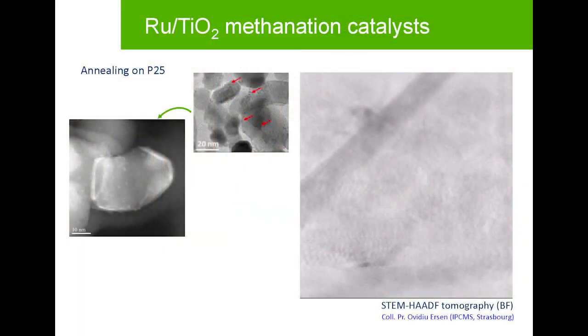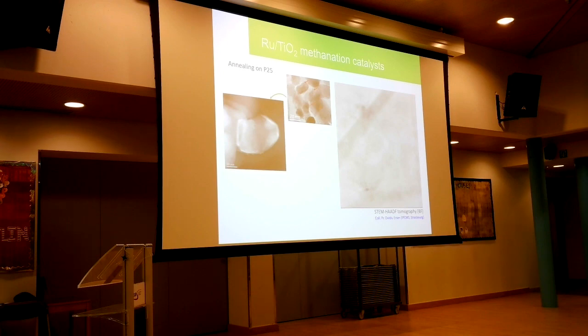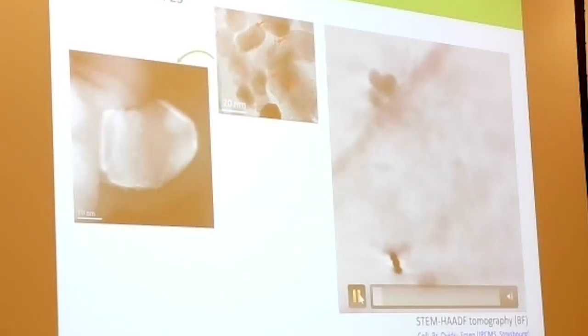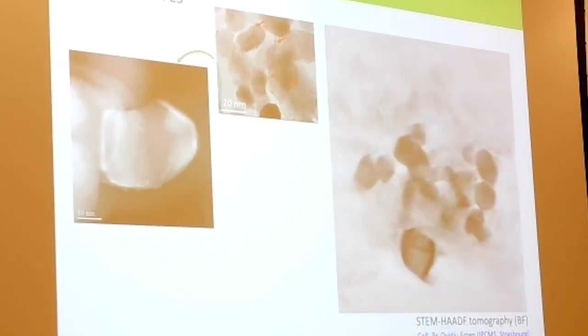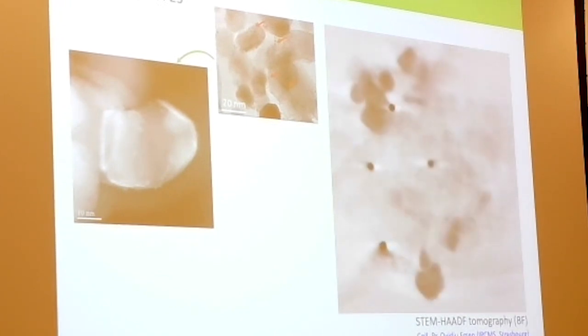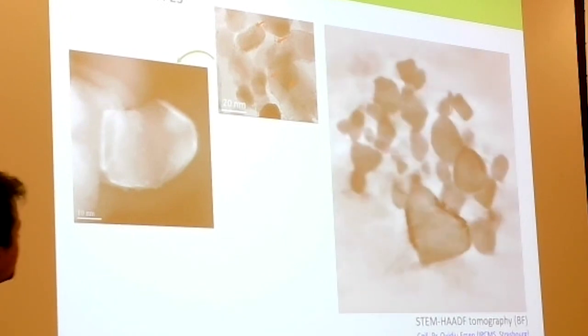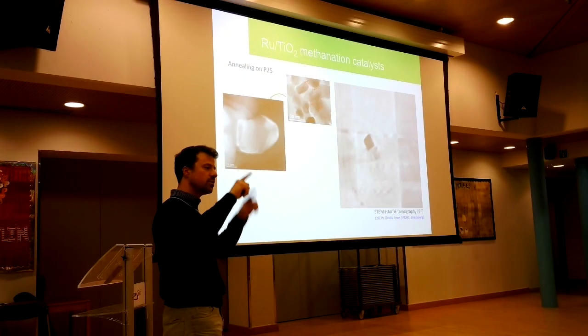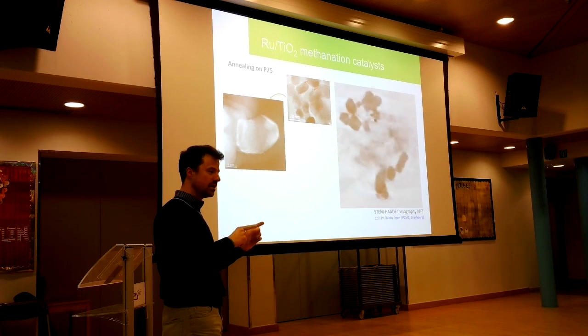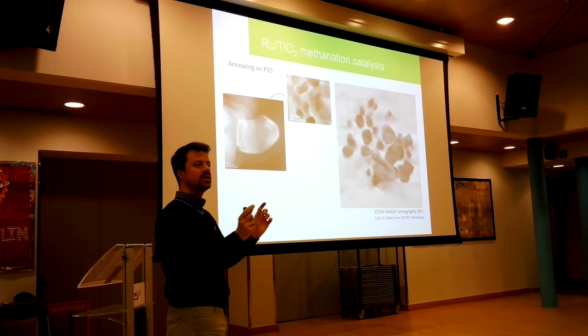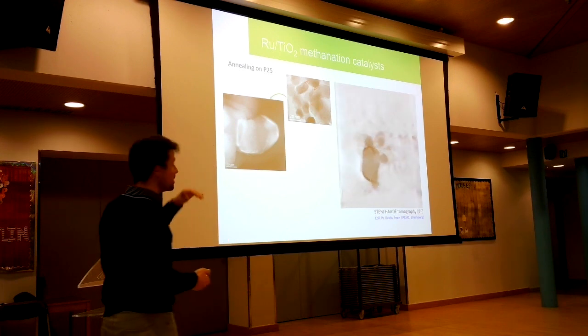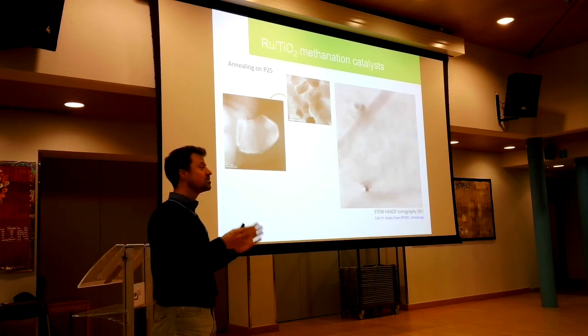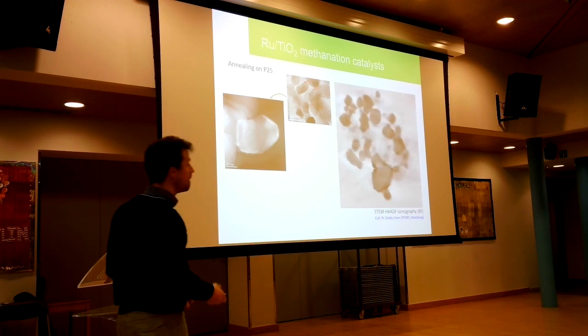In fact, what we realize is that we start with the situation where we have ruthenia everywhere, but after annealing, if you look carefully, we have some particles which have a dark edge, and some others which remain completely clean. So actually we could see that those with a dark edge were titania rutile, so the phase for which there is an epitaxy or an affinity with the ruthenia phase. And the others were anatase, because ruthenia does not like anatase, it likes rutile, okay?